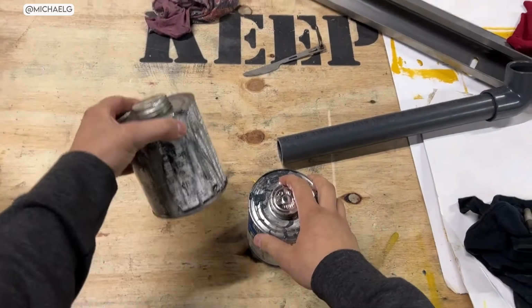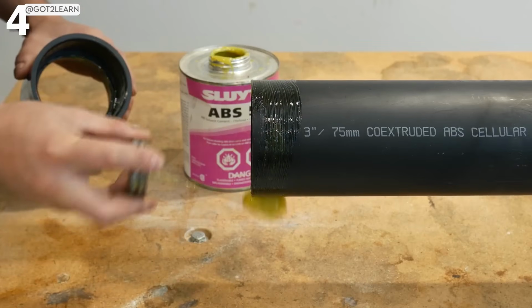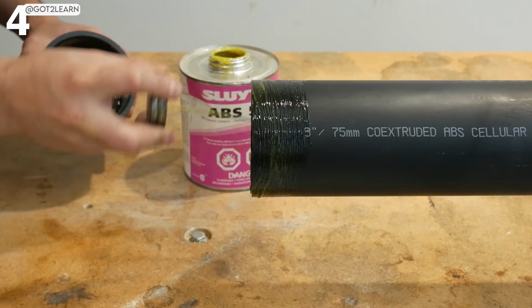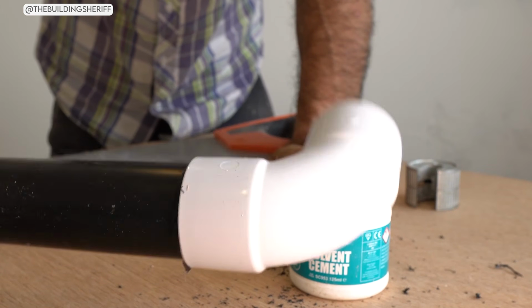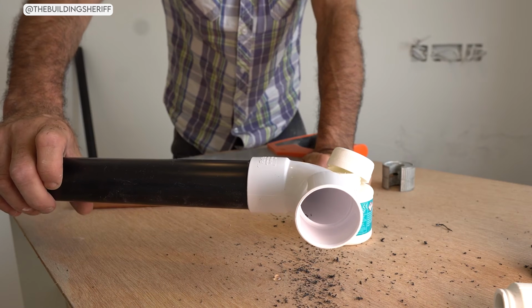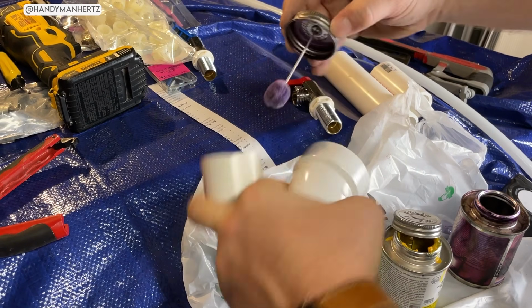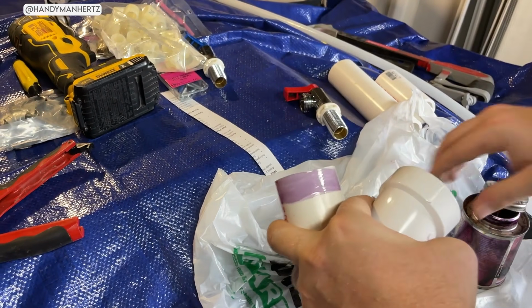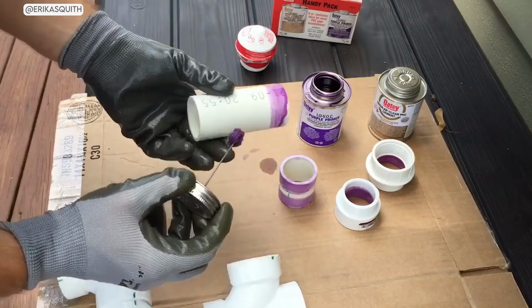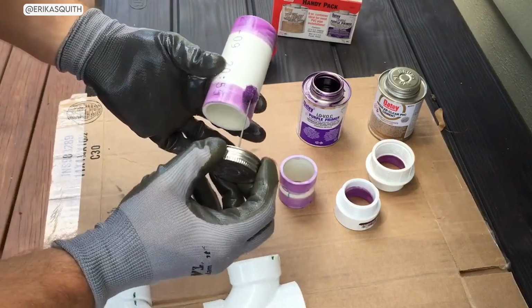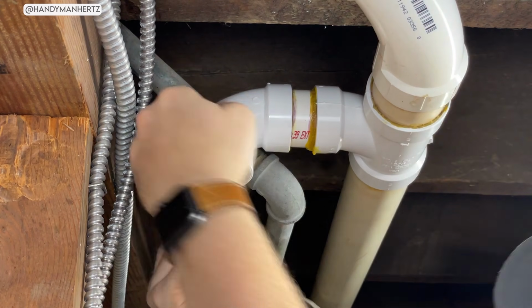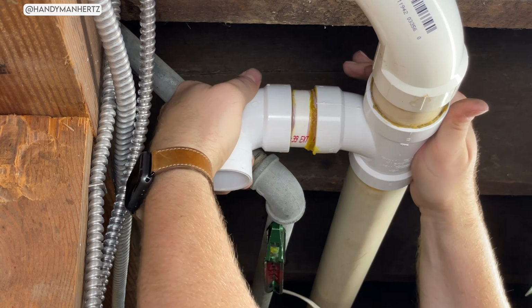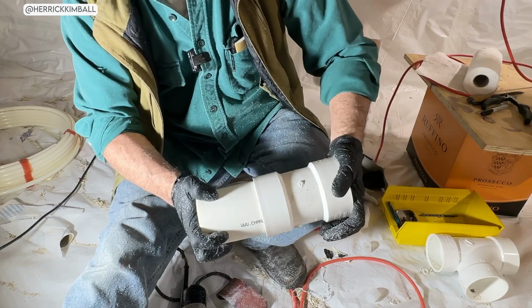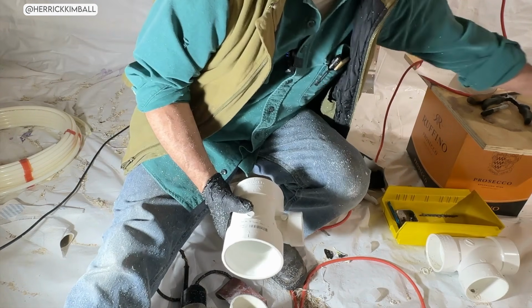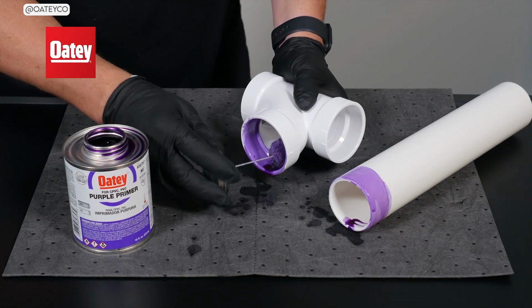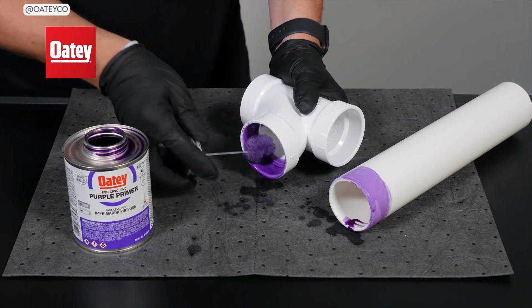CPVC cement is a different formula for CPVC pipe. ABS cement is for ABS. Using PVC cement on CPVC joints results in a bond that appears complete but lacks the chemical compatibility for a true solvent weld. The cans look similar, the colors vary by brand, and in a dim crawl space, it is very easy to grab the wrong container. Mark your cans clearly before the job and keep PVC and CPVC supplies physically separated in your tool bag. If you are transitioning between PVC and CPVC with a mechanical fitting, use the appropriate cement on each side based on the pipe material at that connection.